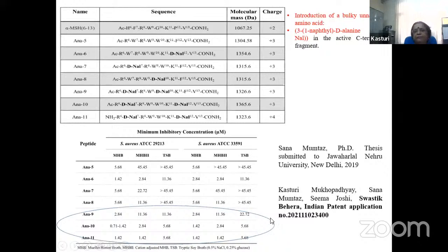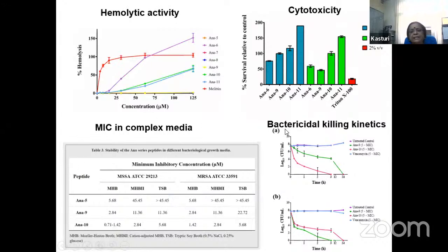And if you see, in complex media, for the first time we have shown that ANA9, ANA10, ANA11, these peptides based on alpha MSH, can give the MIC at a very manageable concentration. It is very important. You see, the MIC is in the range of even 1 micromolar. So we have patented these 3 peptides very recently. Not only that, they have very little cytotoxicity, and they cause killing of Staphylococcus aureus from 8 log to 3 log, a 5 log killing we have shown.